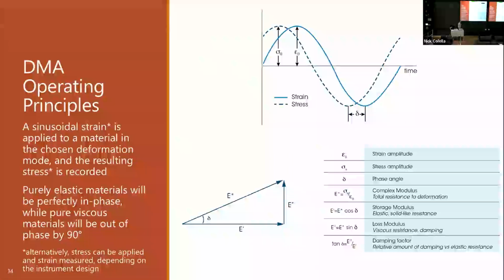Complete overlap, exactly. So if we have a purely elastic material, the more stress we have, the more strain we have, and vice versa, and they're always going to go together. If we have something that's a pure liquid, we can't put pure liquids in the DMA, we can put them in the rheometer, which operates similarly. But if you have something that's purely liquid, we're going to get this perfectly out of phase because of the way that the strain rate and the motion of the material is going. For viscoelastic materials, we get something in between, which is interesting, and that's how we get the data.